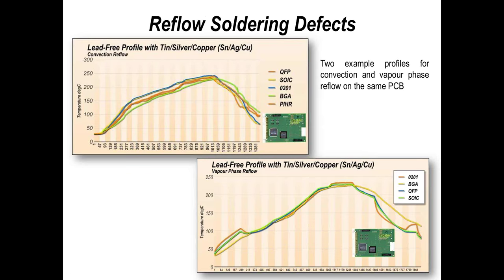Now with reflow soldering, we have lots of options today, and we've obviously seen the growth of vapor phase reflow in the last, I guess, 6 or 7 years or so. Originally, vapor phase was one of the chosen processes right at the very start of SMT. It's certainly my process of choice at the very start of my career on reflow soldering, as opposed to infrared. Convection is the dominant process within our marketplace. You tend to find that the majority of companies use convection in air, and that tends to be what I see more than anything else. And that's not saying that that's the best process, it's just a fact of life.